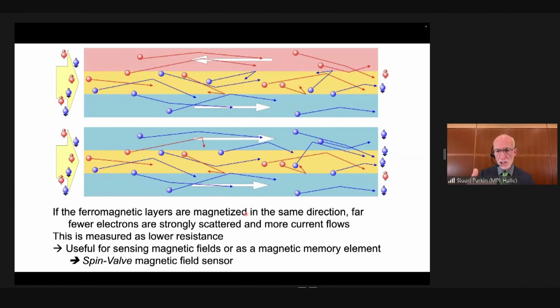So the resistance of the top structure, in which the magnetic moments are anti-parallel to one another, will be higher than the bottom configuration of the magnetic moments when they're parallel to one another. And so this means that the resistance of this device can be changed by an external magnetic field, which changes the relative orientation of these two layers. So we can build a sensing device.